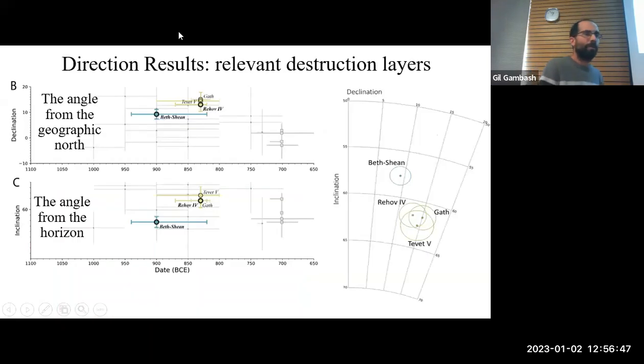When we look at our results, we get a completely different picture. Here you see the direction results. So this is Beit She'an here. This is inclination and declination. This is not a very big difference, but still a difference. This is the date and the inclination, declination here. And this is the equal area projection, where this is north. So we have positive declination to the east in both of them, but you can see the declination in these three sites is bigger than Beit She'an, and the inclination is significantly higher. It's more than 60 degrees down, and this is just 55. There is a significant difference here.